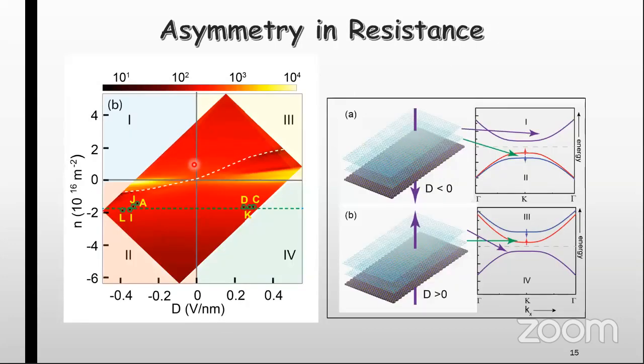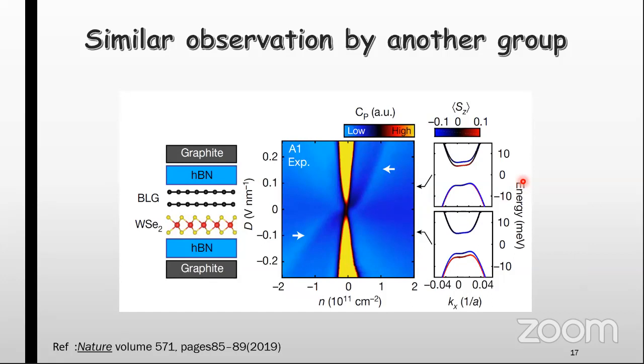So let's understand this. Let's say we are in this region 3, where the displacement field is positive and our Fermi energy is lying in the conduction band. In this case, we should have a stronger spin orbit coupling in the conduction band, and that should be split. So instead of having a single band edge, we should have a double band edge, and that is what is reflected in the resistance plot. We also observed this for region 2, where the valence band is showing the splitting. There is a similar observation by another group who did a quantum capacitance measurement for the same kind of heterostructure, and they also found an asymmetric feature as a function of displacement field depending on the splitting in the valence band and conduction band.